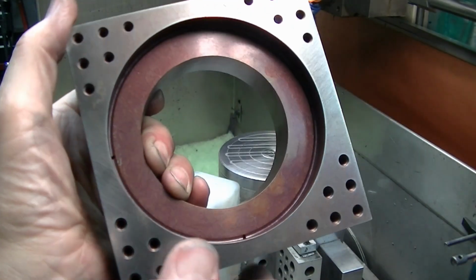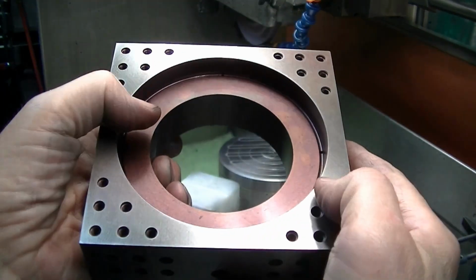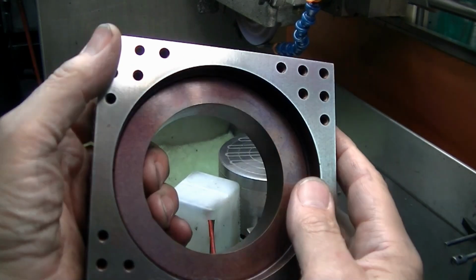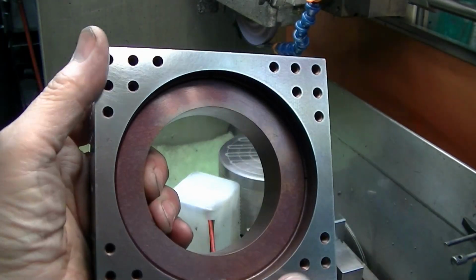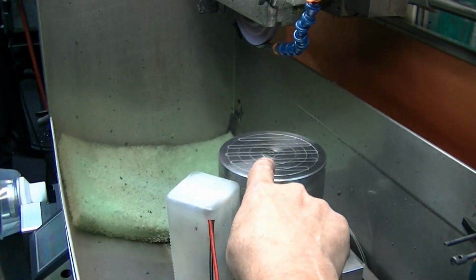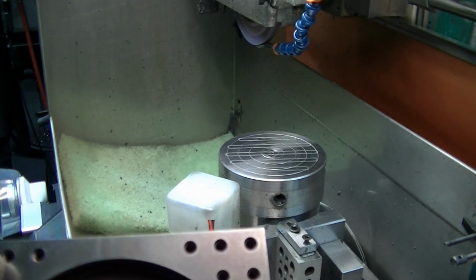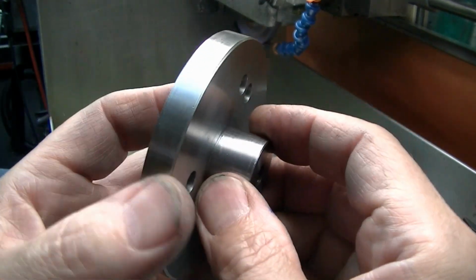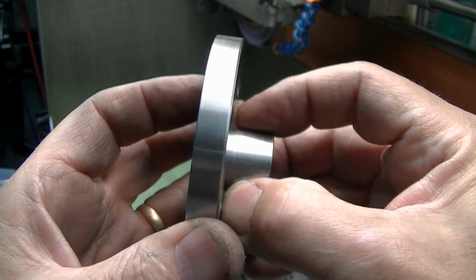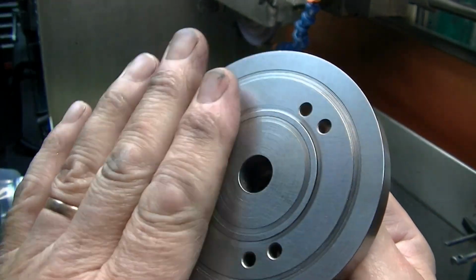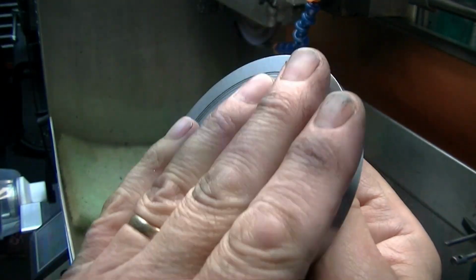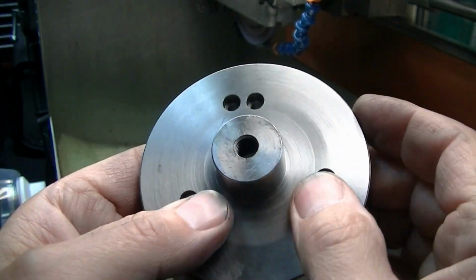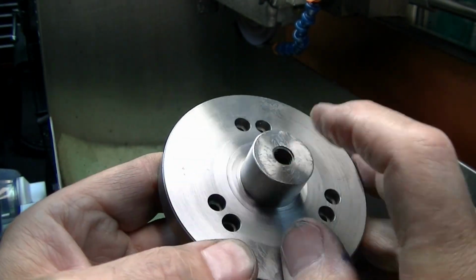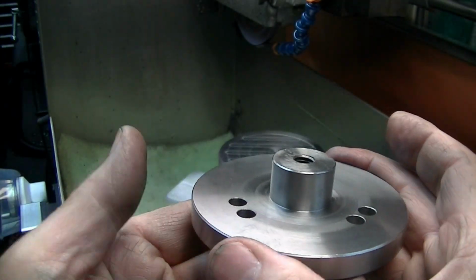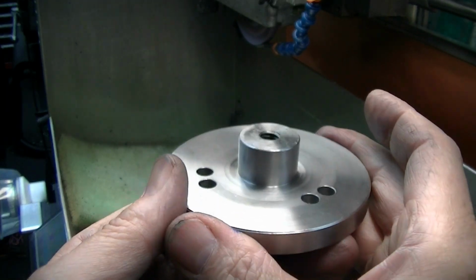Here's our 5-inch Toolroom spindle body. But the problem here is this hole completely misses the magnetic lines of flux in this chuck. So what are we going to do? We have this fixture plate that I use grabbing a 1-inch collet here and bolting things on the lathe. So this is nice and flat, been on this magic sanding plate, has a 3/8-16 tap hole, and this fits inside that housing without hitting anything.